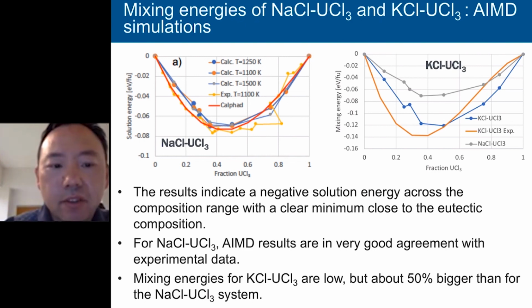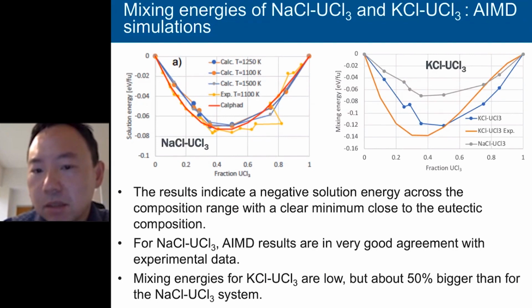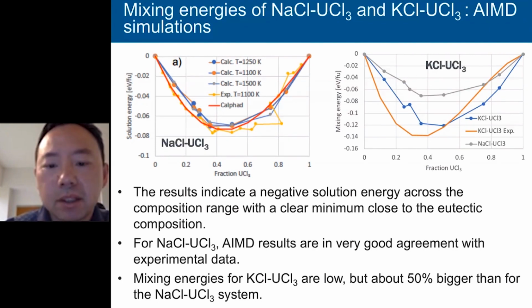So again, if you look at the Ab-Initio results, they compare very nicely with the experimental data and also cover the modeling, which is very nice. So this shows that this kind of modeling can be very useful to provide thermodynamic data when these data are not available experimentally.